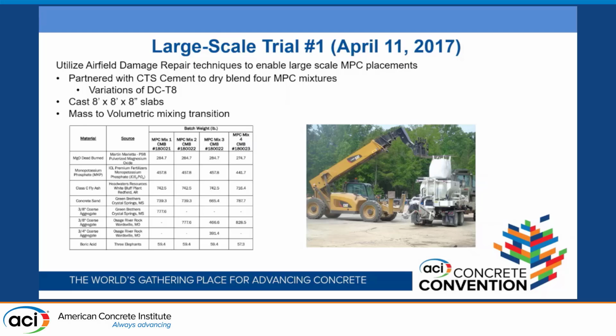So we did this out at our test site called Poorhouse. We partnered with CTS Cement to dry blend our materials at our mix designs. And then it was 4 variations. We did 4 variations of that DC-T8, and we cast 8 foot by 8 foot by 8 inch thick slabs. And a big key to this was everything I had done in the lab to this point was all mass. It was all just going into a regular concrete mixer. So we also had to evaluate how that mass proportioning transitions to a volumetric proportioning. And so the 4 different mixes we tried, the first three are variations of DC-T8, but with different aggregates.